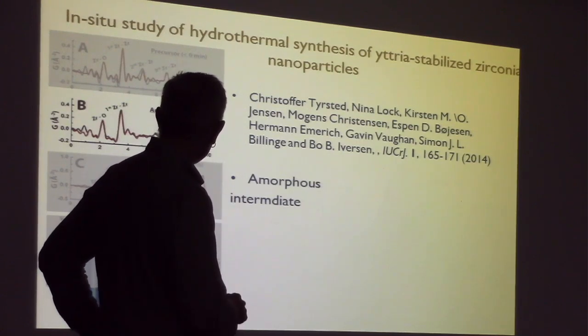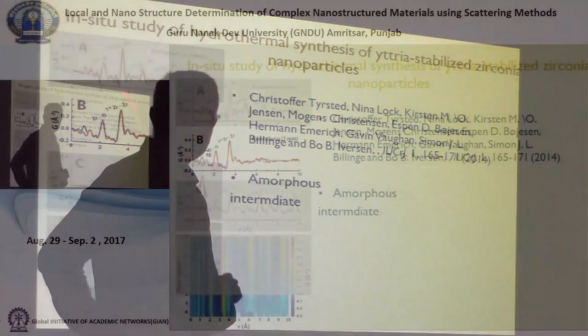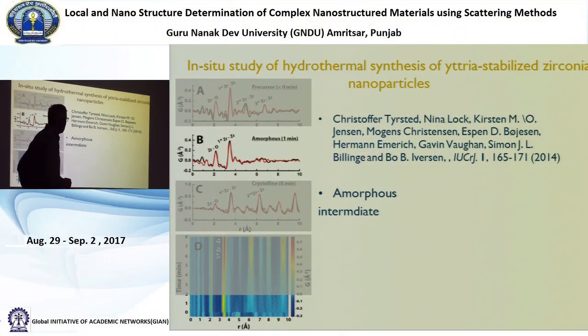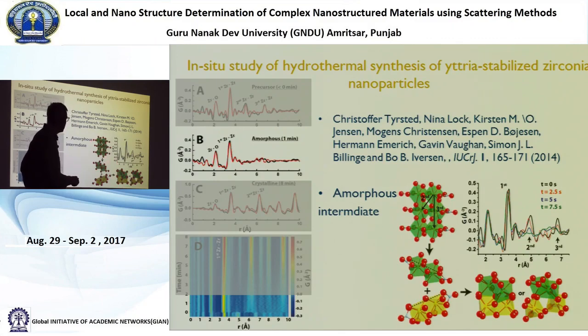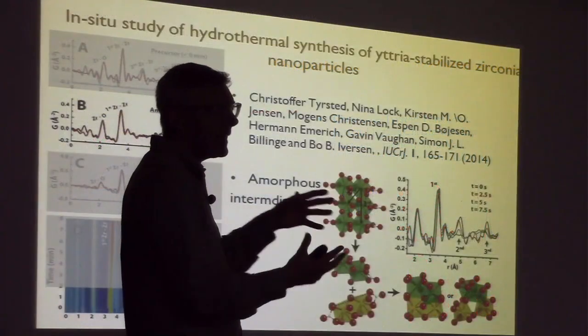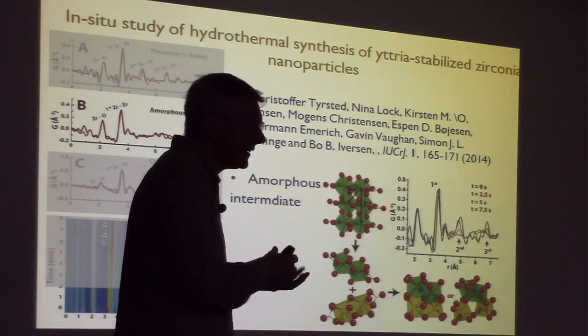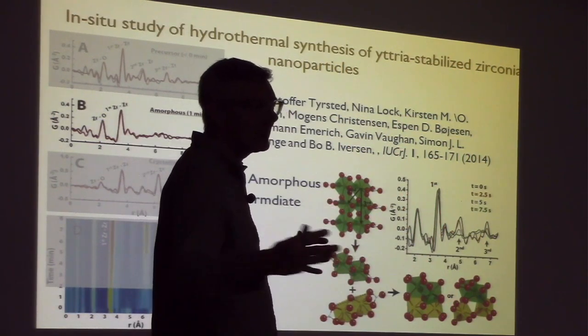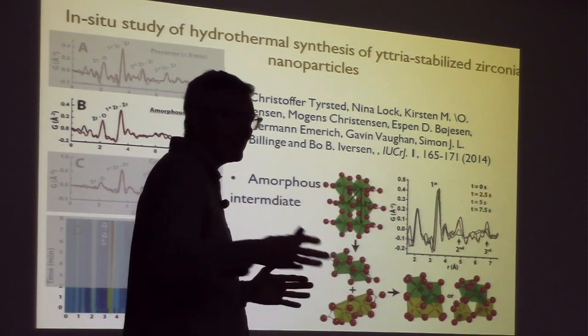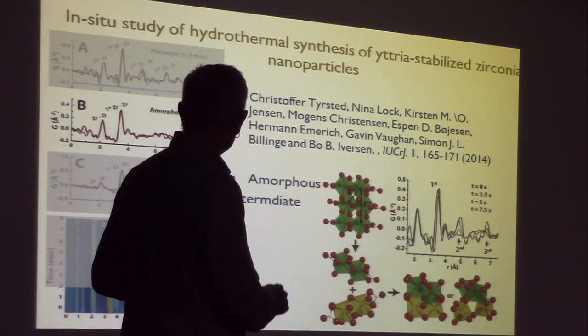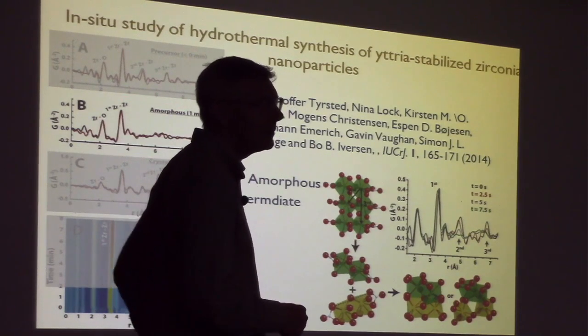And in the next period, what we see is these peaks start to disappear, and we get something that looks like amorphous material. And so what we think is happening is that these polymerized objects, the dimers, are coming off the object, and then the dimers are fitting together to make a product. And there's more than one way that they can fit together. To form the perfect crystal structure, they'd all have to clip together in exactly the same way. But they come off and they just find a neighbor and pair with the neighbor and they make mistakes. So when they start coming together to form larger objects, it can't propagate the correct structure over long range. So it basically forms this amorphous intermediate very, very rapidly.